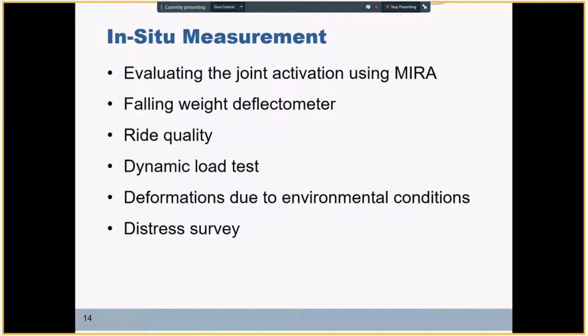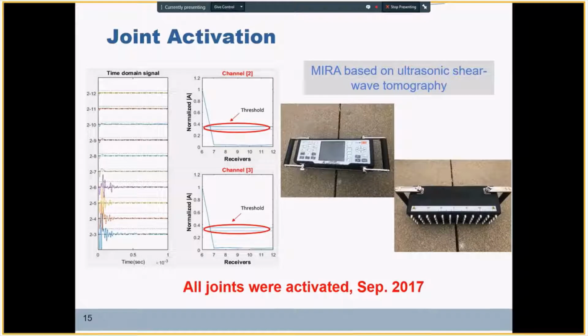First, I'm going to go through the joint activation data obtained using the MIRA system. In September 2017, about a month and a half to two months after construction of the pavements, we went up there and used the MIRA system, which is actually an ultrasonic shear wave tomography method, to see if the joints are activated in these two pavement cells. Each cell is about 260 feet long, with 15-foot joint spacing, giving us about 17 to 18 joints in each cell.